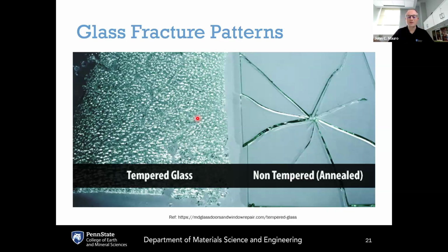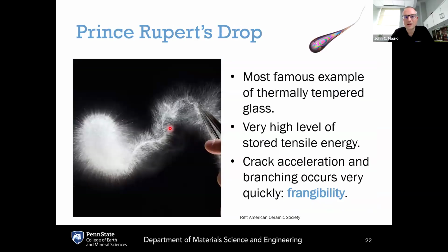They continue to release the tensile energy, continue to accelerate until they reach their terminal velocity, and then they will branch again. And as a result, the pattern that you get from tempered glass failure is these very small shards, and this is what's called frangibility. And this is because of the release of tensile energy.